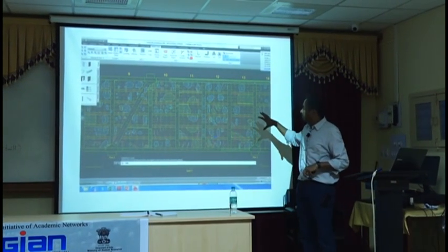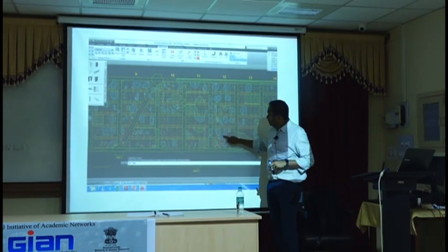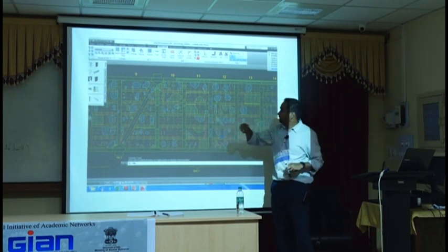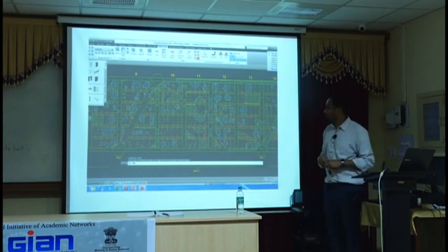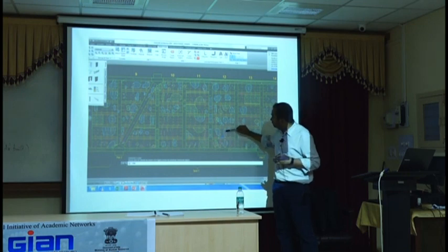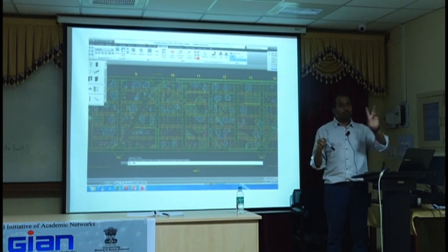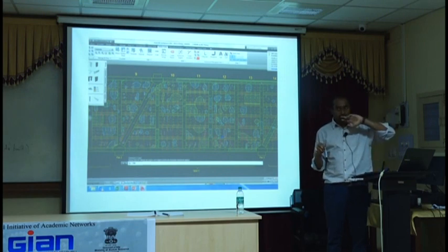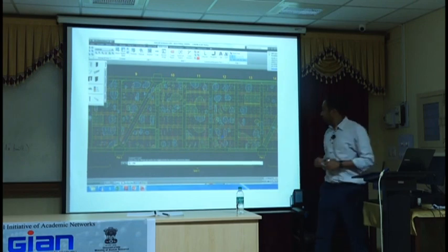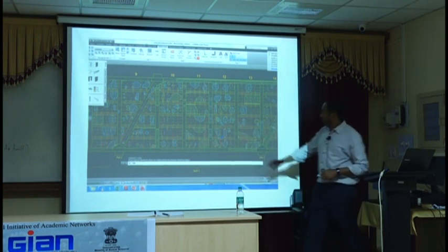This is how the half cell potential mapping looks, and that's probably what we normally do. So the individual values are recorded here. Different color means different test, but these contour maps indicate delamination, and the individual values with the color indicate half cell. What we were looking at is wherever half cell changes from positive to negative, because that boundary is interesting for us. That means there is an anode and a cathode somewhere there. And that's the two colors. The red means it's negative, and the yellow means it's positive.